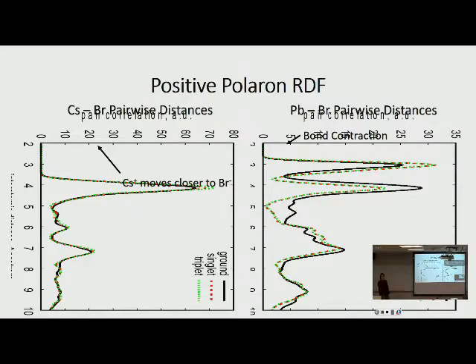Okay. So if it would be larger displacements away from the center... Oh, these would be increased too. No, if it were not a polaron but some crazy noise, the green and black or red and black curves would have substantial difference at larger interatomic distances. But the curves kind of converge. They have some difference at lower values of the argument, and then they stop changing from each other.